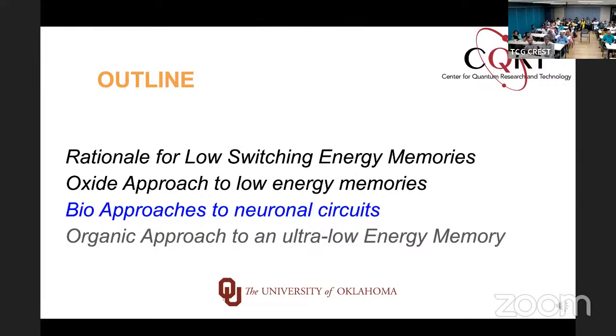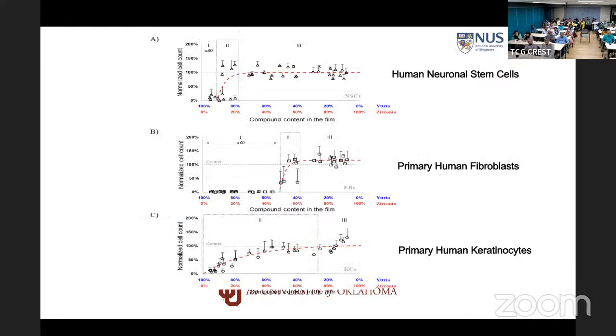I thought it was a very cool idea. But the point is, how do you force the neuron to stay where you want it to go? So we started looking at the growth of cells on various oxide surfaces. We deposited amorphous oxide layers and grew cells on them. We noticed that cells have strong preferences for which oxide they like to grow on or don't want to grow on.